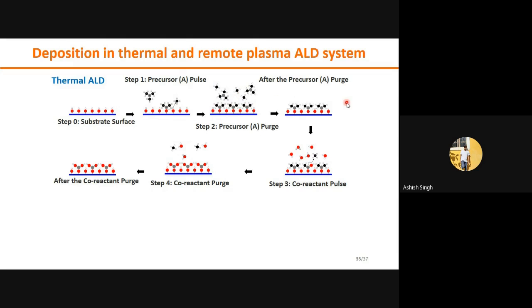So we remove it through purging or evacuating the chamber. Then second, this is the monolayer of the metal precursor. Then to complete the reaction, we need to put in water vapor, and we get a single layer of the material. Then again the leftover metal precursor needs to be removed, so again we need to purge. This is the typical thermal ALD sequence.